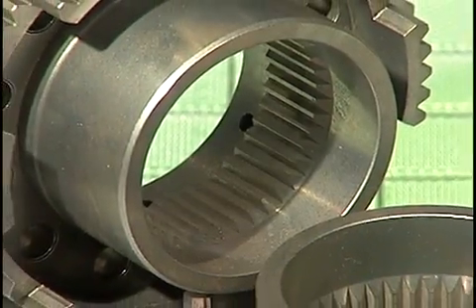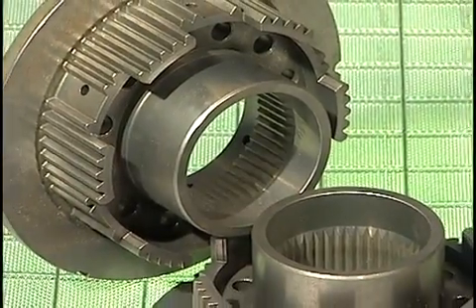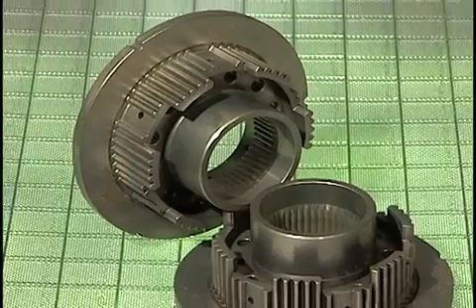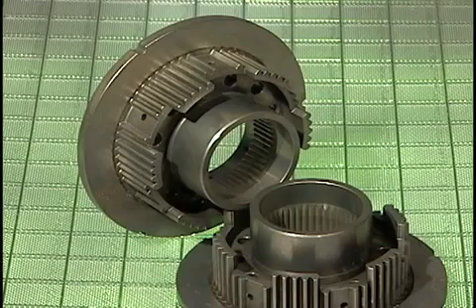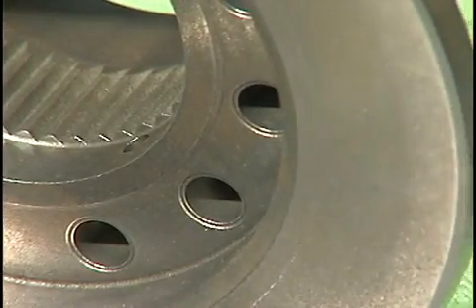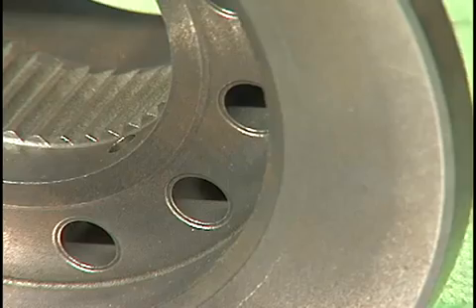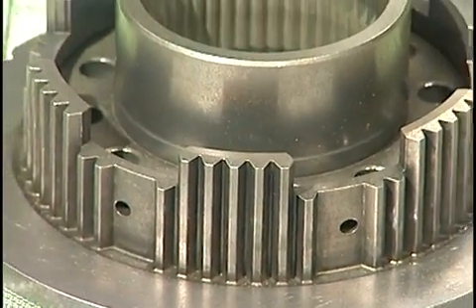A minimum density of 7.0 grams per cubic centimeter, 165,000 psi tensile strength, yield strength of 150,000 psi, and an apparent hardness of 35 HRC. The complex castellated geometry required innovative tooling to precisely control lengths, diameters, densities, weight, and runout, as well as an even density distribution throughout the part.